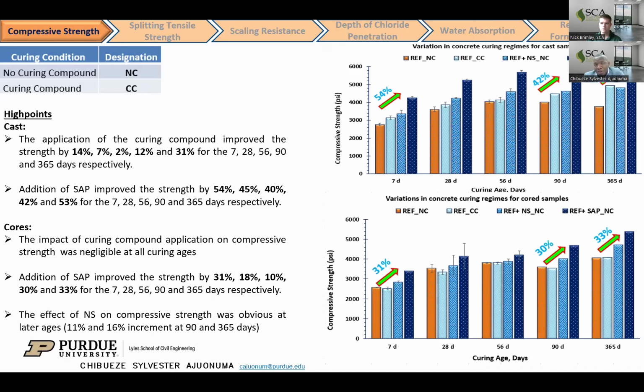We had a 54% increase at 7 days, then 45%, 40%, 42%, as well as 53% increase at 28, 56, 90, and 365 days, for the mixes that had the SAP in them.